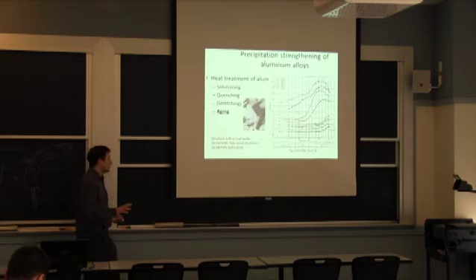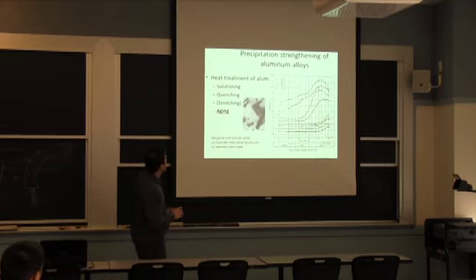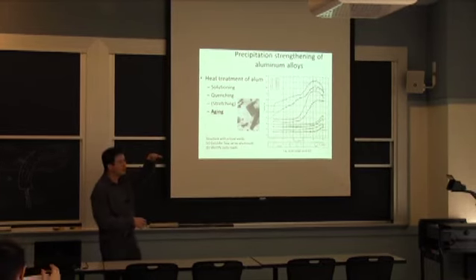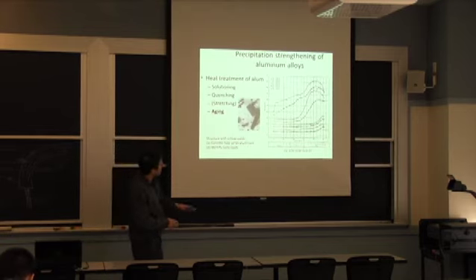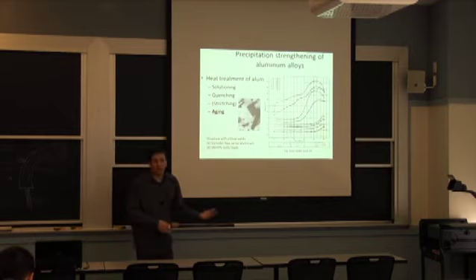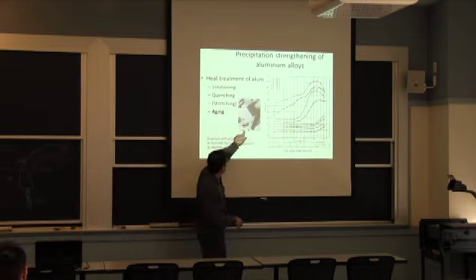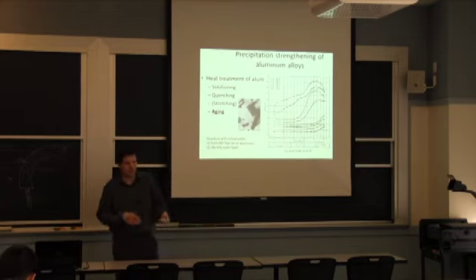So I was very serious about how much you can increase the hardness by these little heat treatments we talked about. So we talked about solutioning it, so heating it up in a region where both the copper and aluminum share the same crystals. They all agree with each other. You quench it, nothing happens. It doesn't harden, it doesn't go through martensite. You can do your forming if you want. That's what I put as stretching. And the aging gives you these little particles in the system that are copper rich or magnesium rich, depending which series you're looking at.